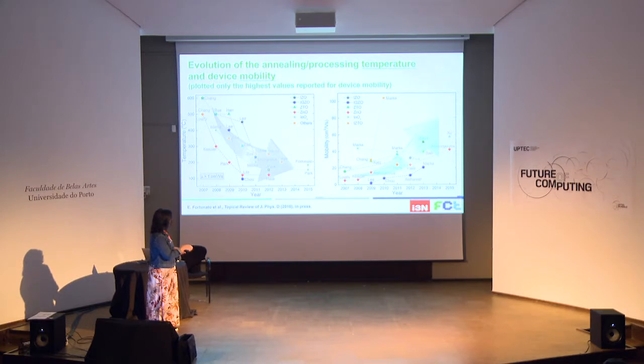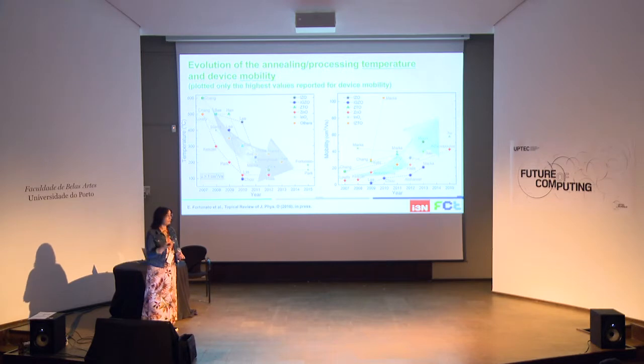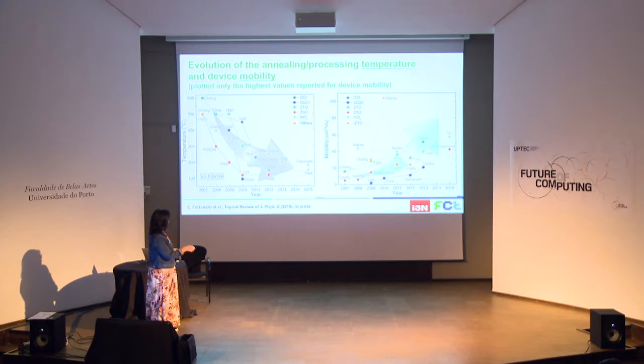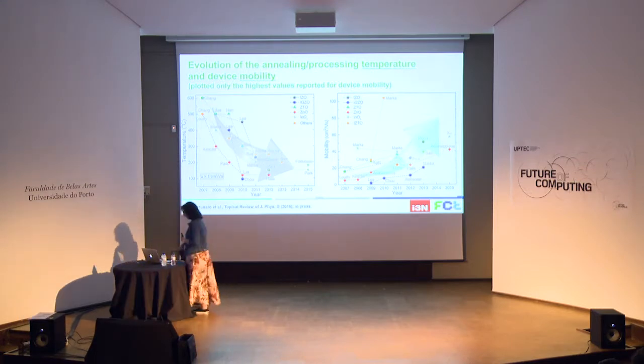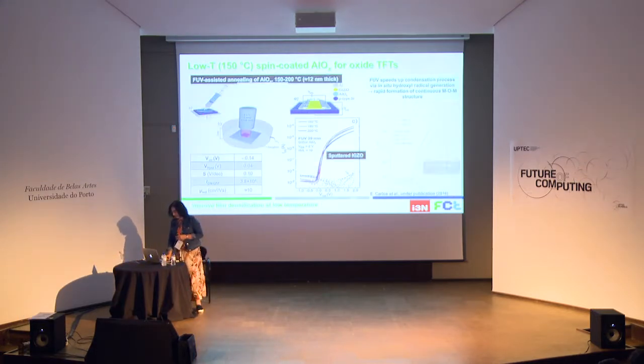And again, the mobility, which is, as I mentioned, the figure of merit of these devices. We observe a decrease in the final processing temperature, and simultaneously an increase in electrical performance. For example, a very famous group from Northwestern University achieved mobilities of 100 using just some liquids and promoting only this type of chemical reactions. So we also built the same.